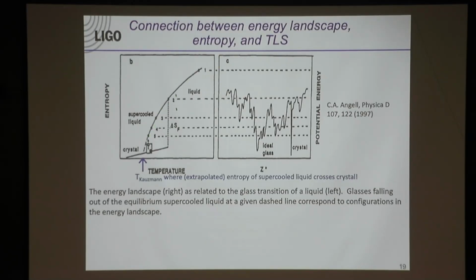And what you find is that in some materials you can follow the entropy down. You never get to the crystalline entropy, but you can get remarkably close, and it's a very short extrapolation. So thermodynamically, you could also say that it is possible to get very close to this ideal glass state, and you can show that through thermodynamic arguments on the entropy.